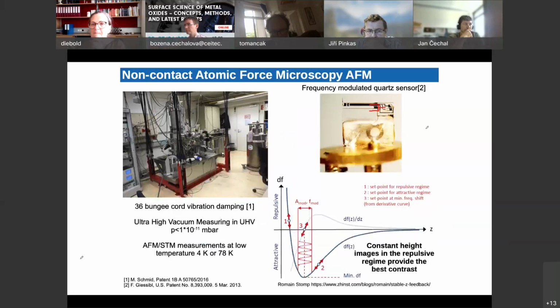And the tip is modulated. The way it's done is that the whole sensor is put on a little shaker piezo, so it's shaken up and down a little bit, which changes the amplitude of this tuning fork, with an amplitude of between, let's say, 0.1 angstrom and 10 angstrom. So you change the amplitude and you measure the frequency change as a function of Z.